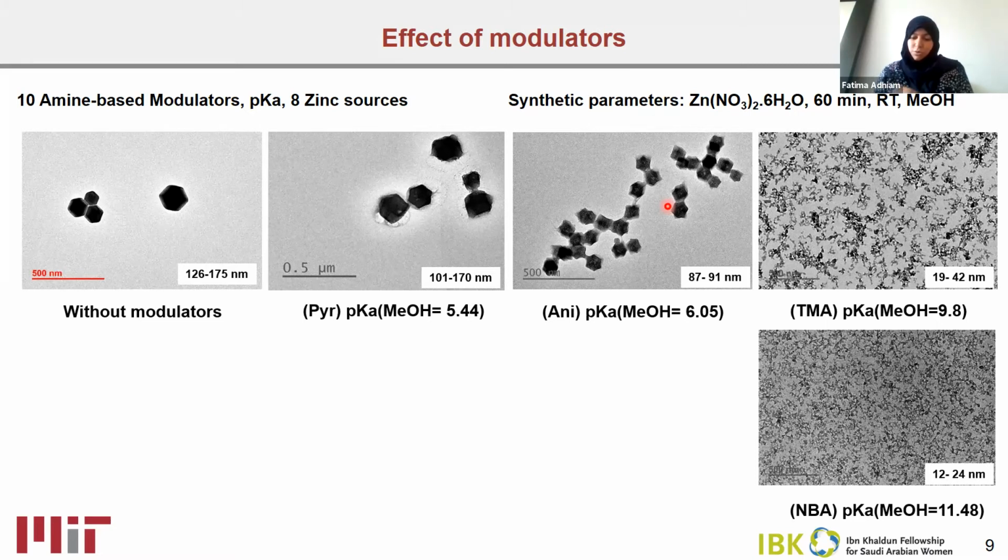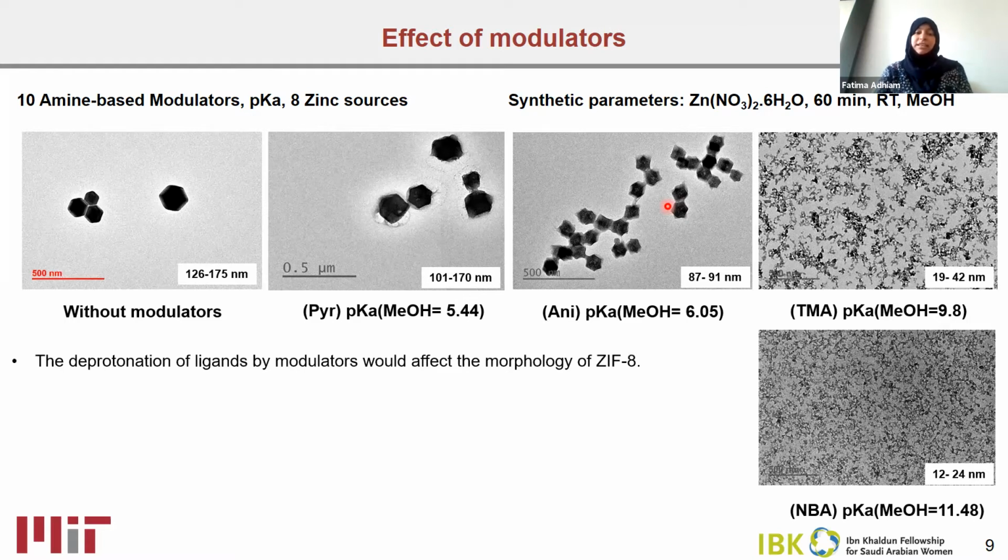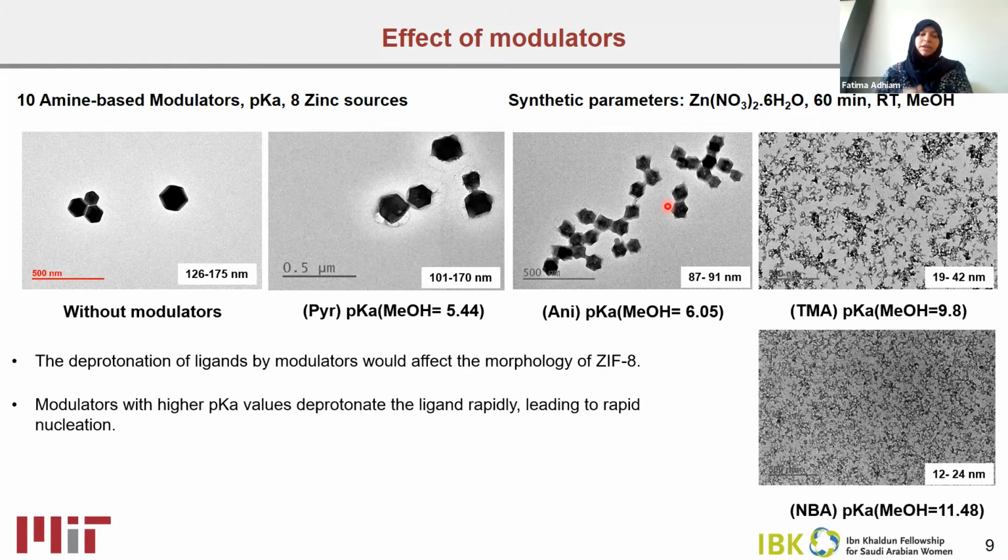As these reactions have been repeated several times using 8 different zinc sources and 10 different amine-based modulators, and we usually get the same trend, we can confirm that the deprotonation of the ligand by the modulator affects the morphology of ZIF-8. Furthermore, a modulator with a higher pKa value can rapidly deprotonate the ligand, which leads to rapid nucleation and a small particle size of the ZIF-8 material.